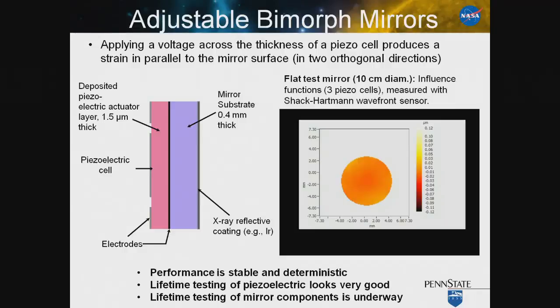What's shown here is the optic itself in a schematic form, where you have the glass substrate. This will be about 400 microns in thickness, with the reflecting surface of a chrome iridium layer. And on the other side of the glass is a continuous bottom electrode, a layer of lead zirconate titanate, where we're currently targeting thicknesses of around 1.5 microns, and then an array of top electrodes that are, in this case, somewhere between 5 millimeters and a centimeter on a side, which we then use to correct the optics. So if I could ask you to go ahead and play the movie here, please.